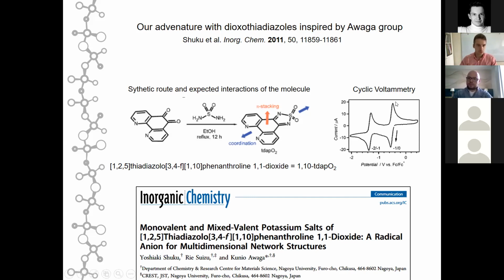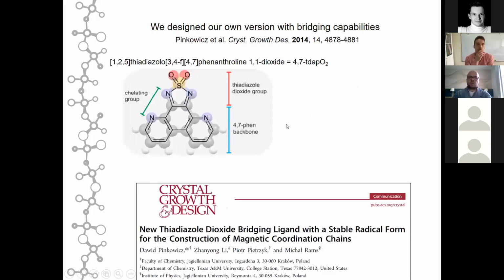And you can see from the cyclic voltammogram that there is an easy way to reduce this system to a stable radical anion. So we didn't actually follow the steps of Kunio Awaga per se, because we wanted to design something a little bit better, something a little bit more useful for the design and synthesis of coordination polymers with this kind of dioxothiadiazole systems.